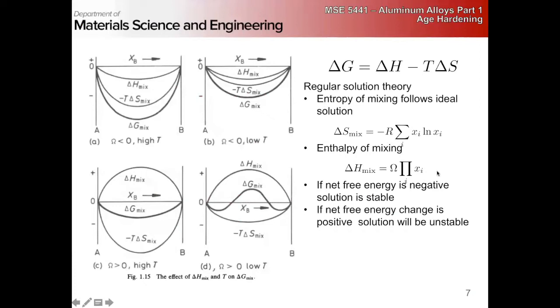But we say that the enthalpy of mixing can deviate. It can be either positive or negative, and we have a factor here out front that describes that. And so if the net free energy change is negative, then our solution is going to be stable. And if the net free energy change is positive, our solution is going to be unstable and will unmix. So our entropy term will always be negative, right? And it will reach a minima at a 50-50. That's where the greatest number of possible microstates are, the number of ways that the atoms of the individual elements can be arranged. If we have a negative enthalpy of mixing, we're going to have a stable solution across the whole range, right?